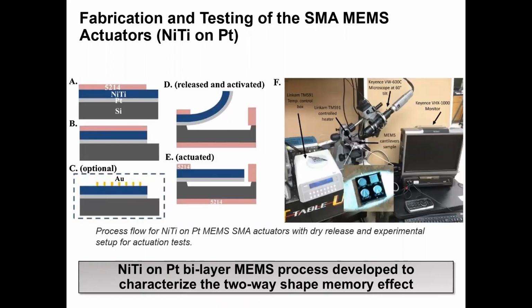And the residual stresses are naturally influenced by the CTE mismatch between NiTi and platinum, and then the crystallization of the NiTi at high temperatures. Shape memory effects and their stress changes in the NiTi film is what caused the devices to actuate when subjected to heating. Then the figure on the right here shows the experimental setups, one of the many which was used to characterize the beam bending and actuation.